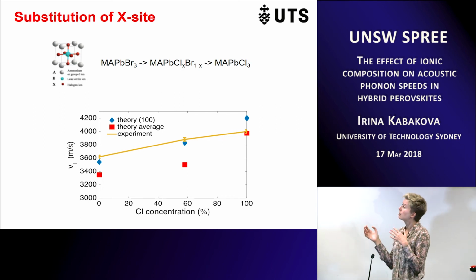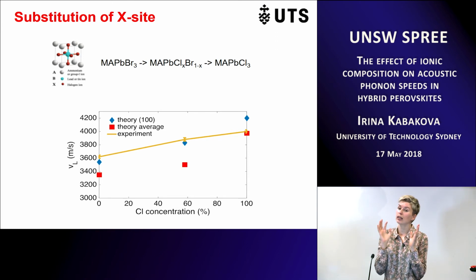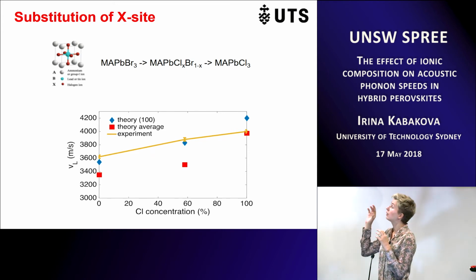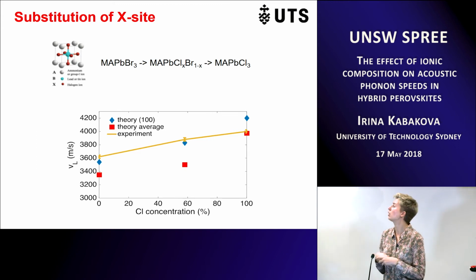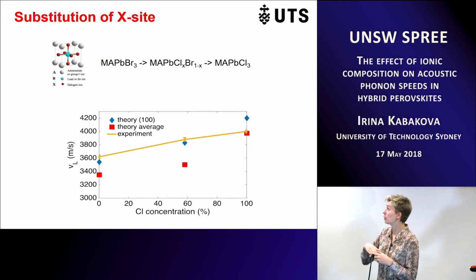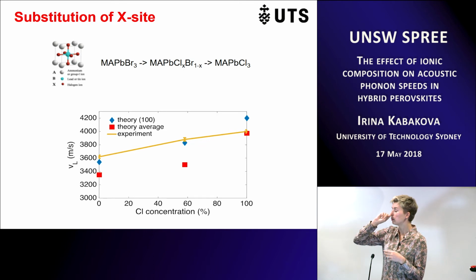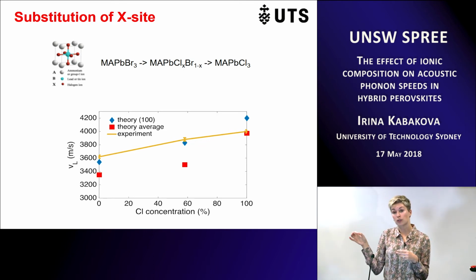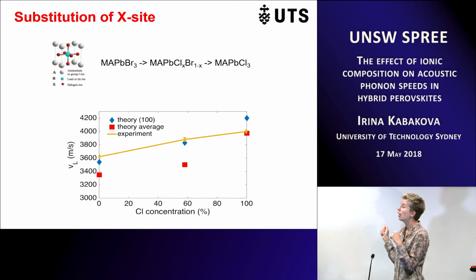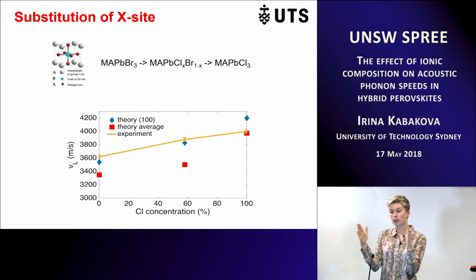And what we see is that bromide, MA lead bromide, is softer. It has lower acoustic speed and lower elastic constant. Chloride crystal is much harder, or stiffer, as you wish, and it has higher acoustic speed and higher elastic constant. What we also know about this range of crystals is that they have different ionicity. So the electronegativity of the lattice is different based on the halogen atom. It also means that the unit cell of the lattice is slightly different as well, right? In bromide the unit cell is larger, and in chloride the unit cell is smaller.